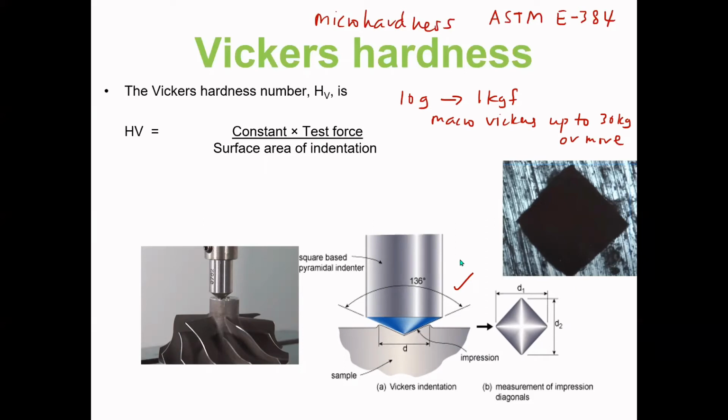So the micro hardness methods are used to test metals, ceramics, composites, almost any type of material. Since the indentation is very small in Vickers testing, these are examples of materials tested by Vickers hardness testing. It is useful for a variety of applications, especially when we want to test very thin materials like foils, or measure the surface of a part, small parts or small areas, when we want to measure individual microstructure, or measure the depth of case hardening by sectioning a part and making a series of indentations to describe a profile of the change in the hardness.